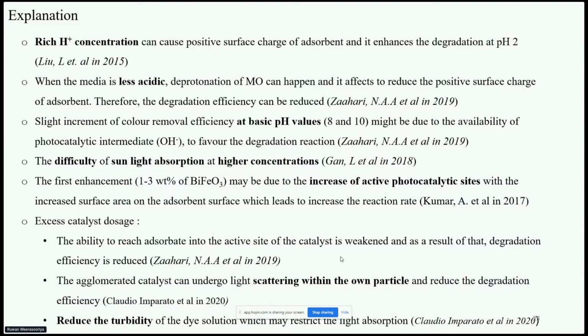That is, when the H plus concentration is higher, the catalyst surface is positively charged. Methyl orange is an anionic dye, and anionic dyes prefer to attach to positively charged surfaces, and therefore adsorption is increased and degradation is improved. At high concentration, the sunlight absorption is difficult and therefore degradation is reduced.